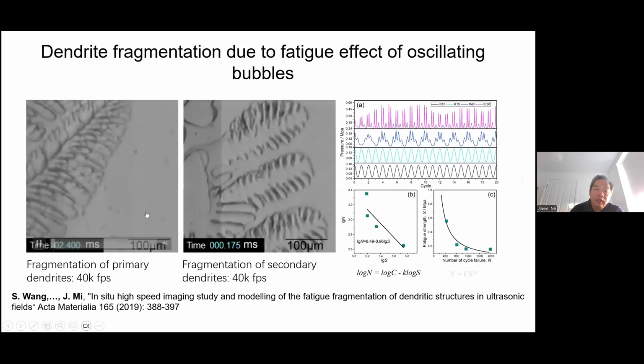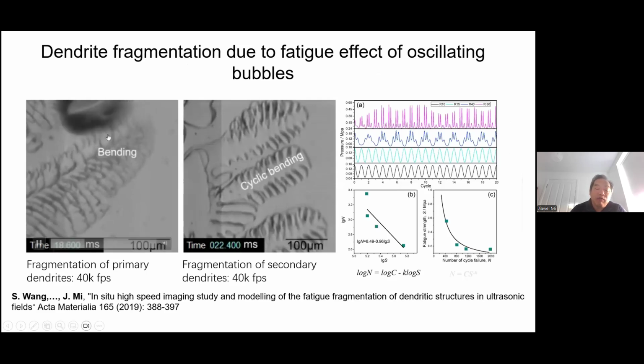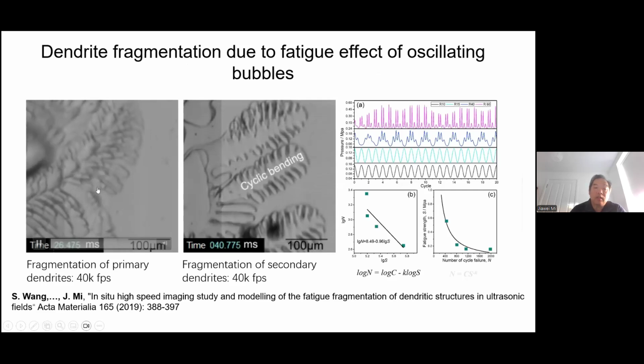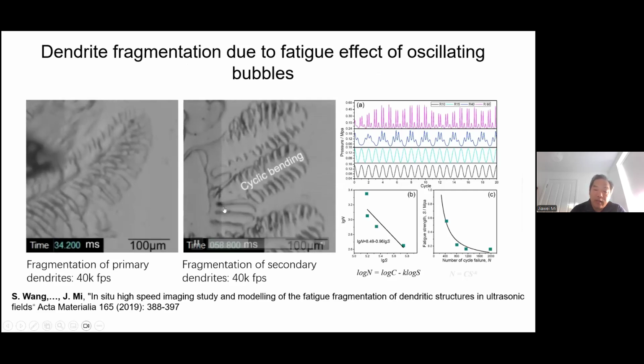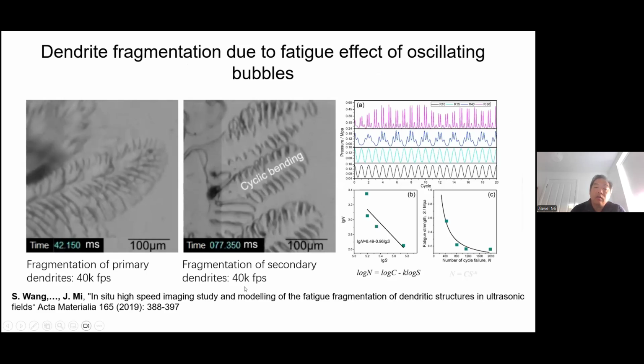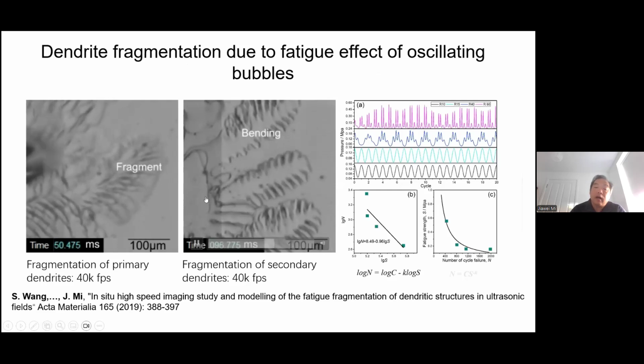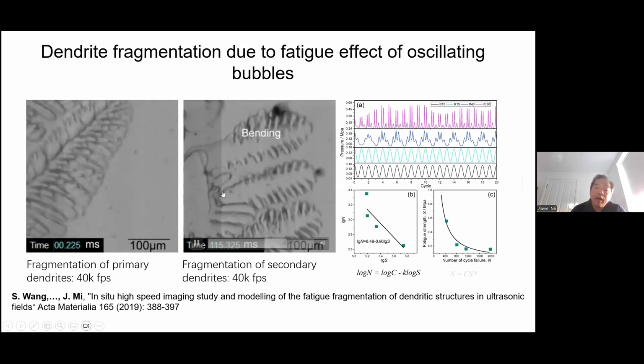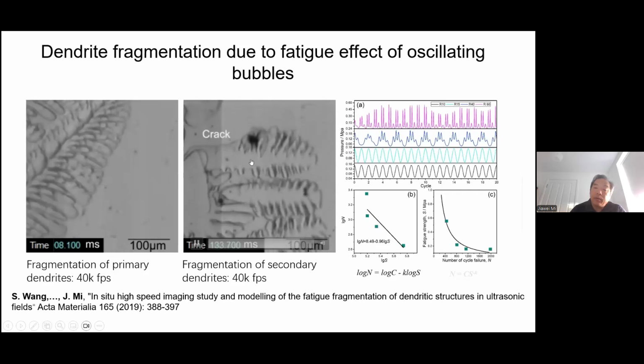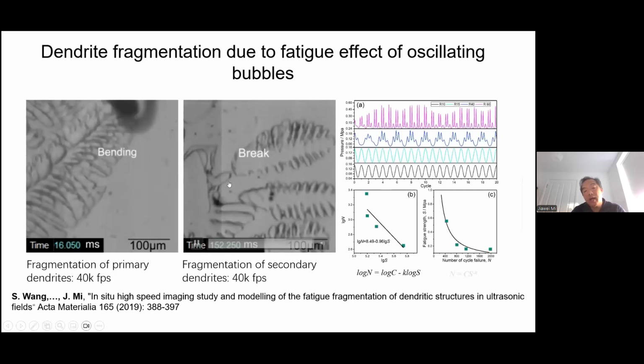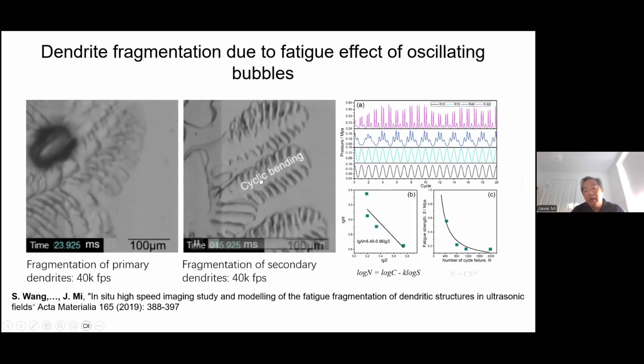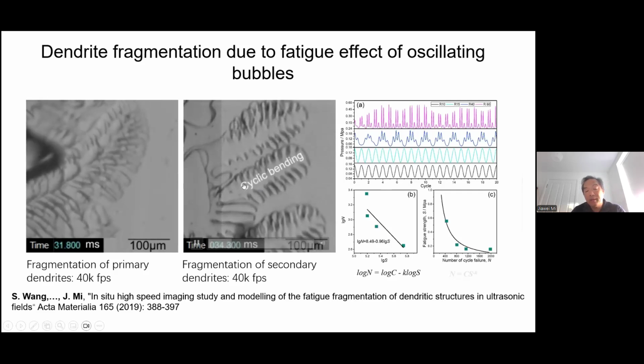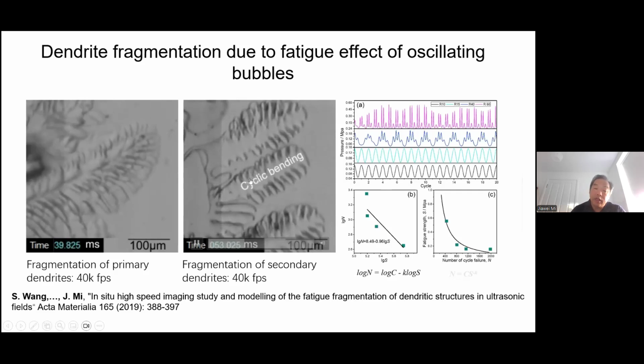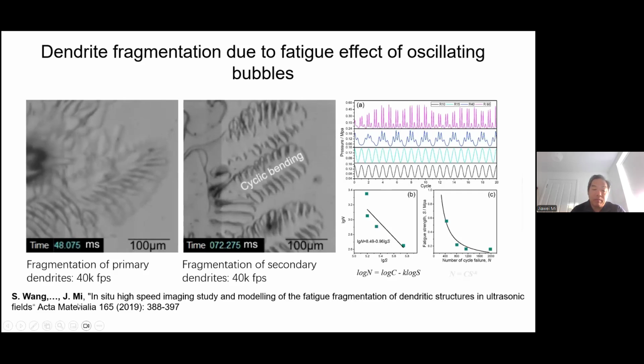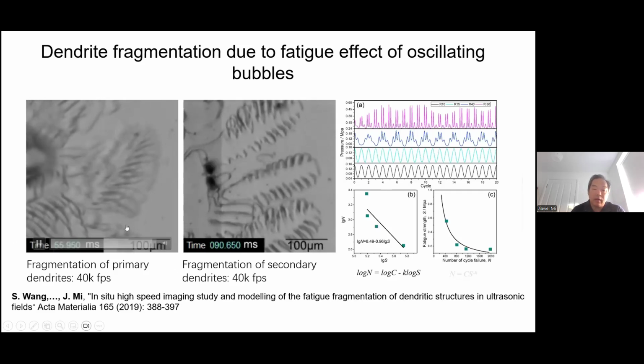But if you look at any individual bubble acting on your dendritic structure, you can see how efficient that vibration is. The bubbles are going to break up your growing dendrite in just a few to a few tens of milliseconds. Basically, this vibration we can use in a fatigue model to understand in how many ultrasound cycles the breakup happens, and then predict this kind of fragmentation life. That's already published in a paper. Interested readers can read those.